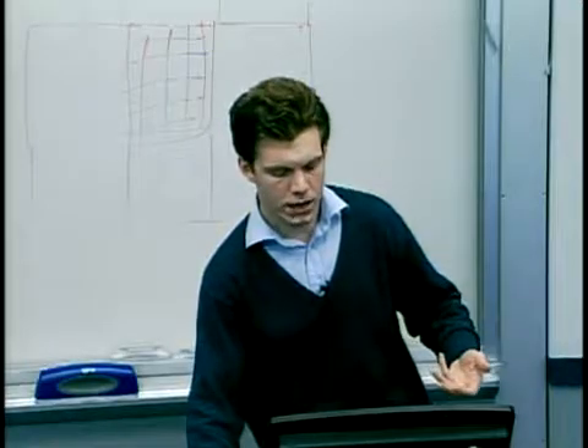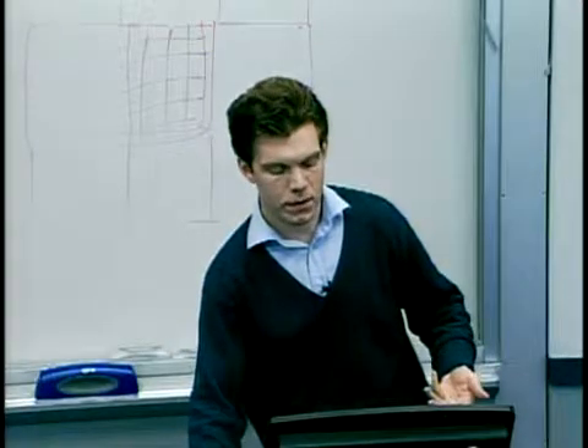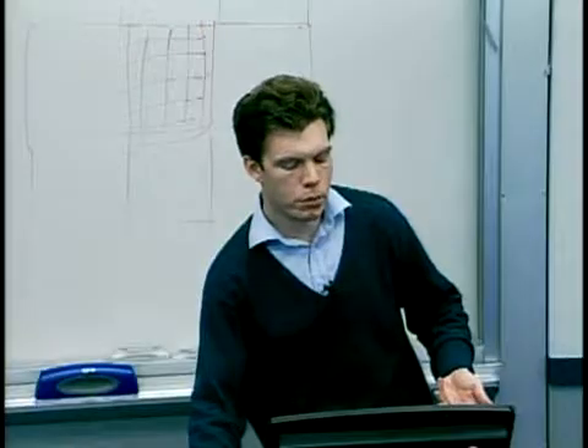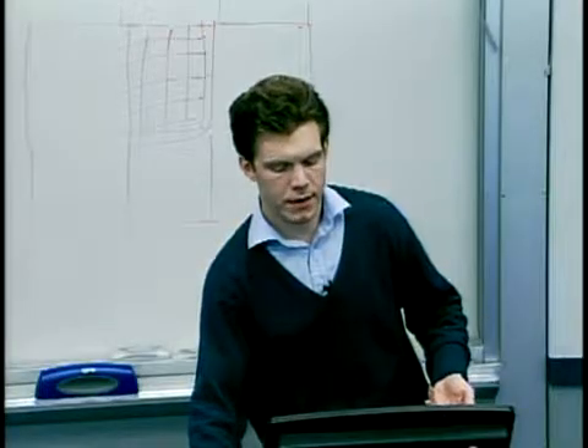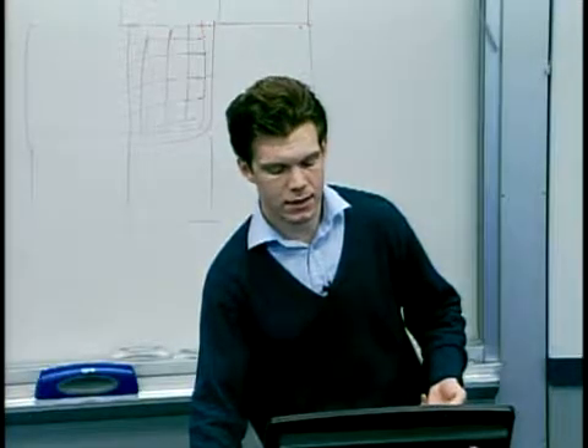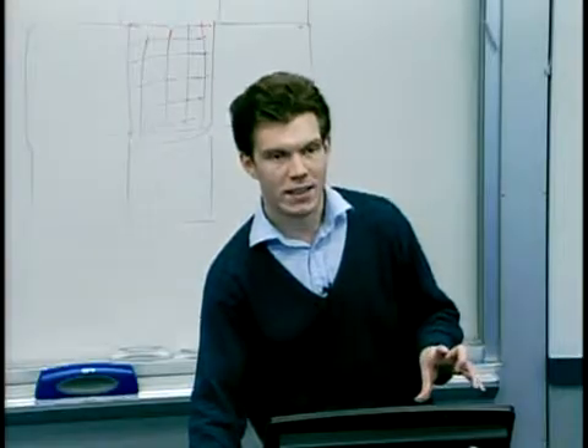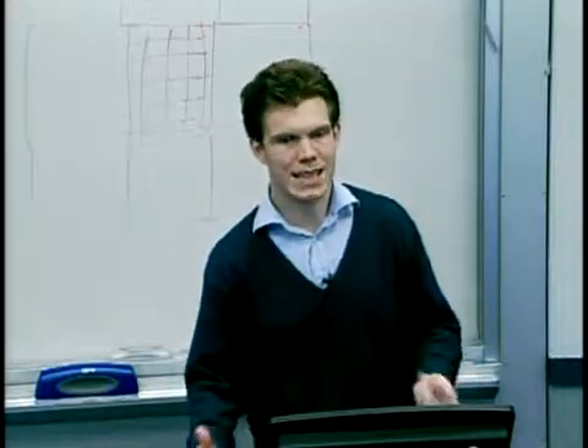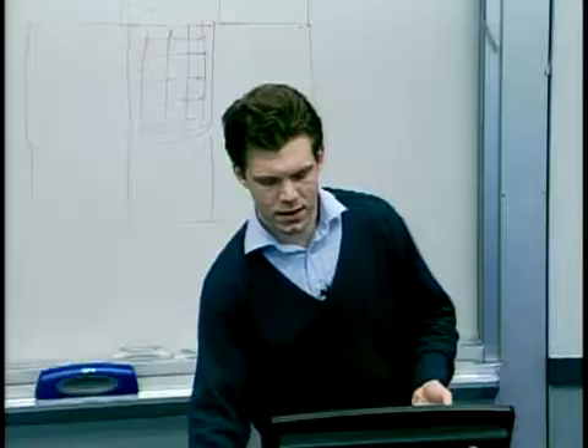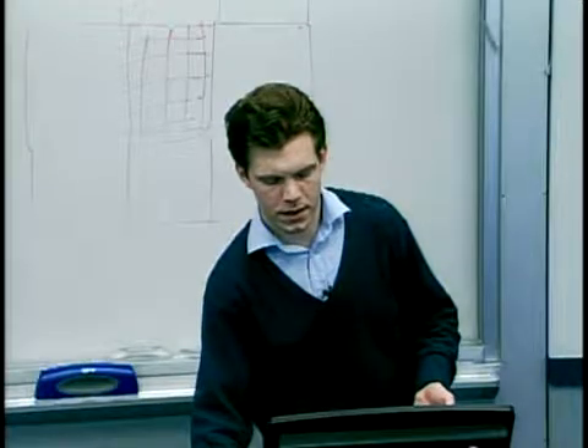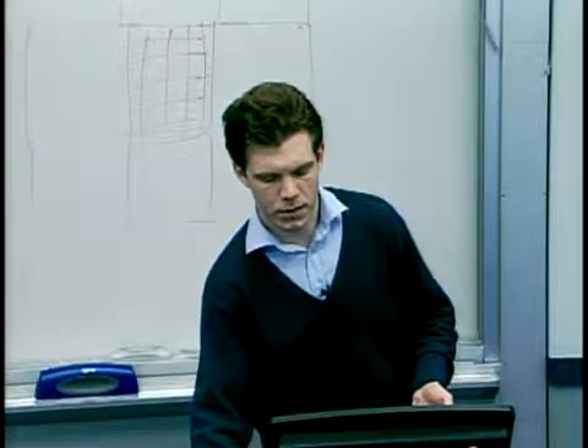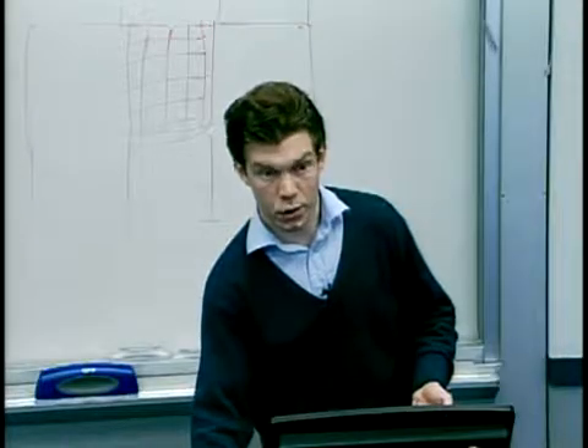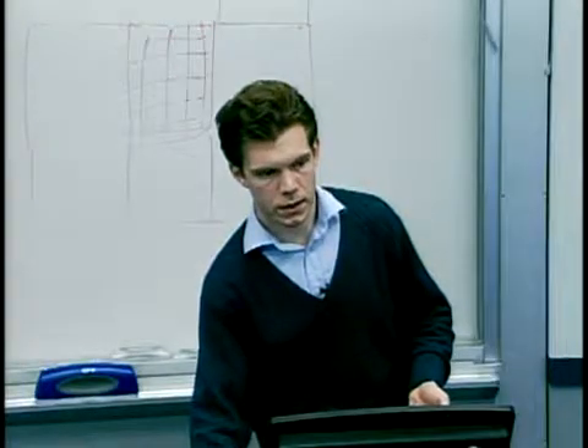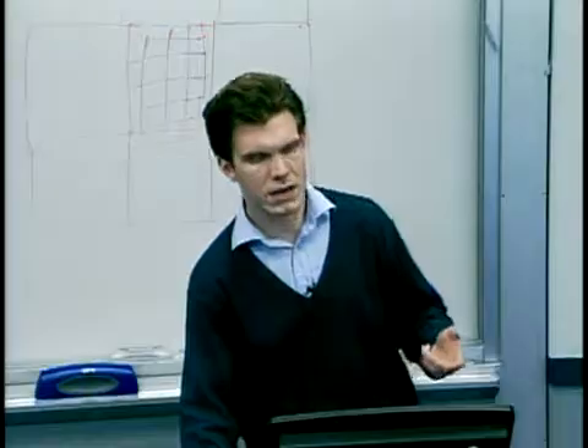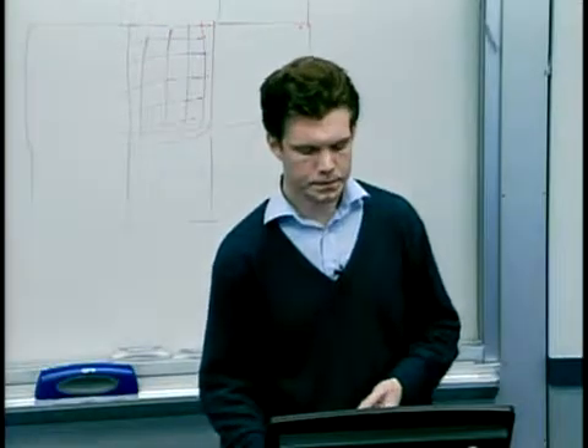And then right up here, you've waited for 10 minutes and all but the smallest features have at least touched the tops of the cavities. Of course, this y-axis is showing the peak penetration. So it's the distance from the top of the feature to the bottom, and it tells you nothing about whether the corners of the features have been filled. But this is a reasonably useful measurement.